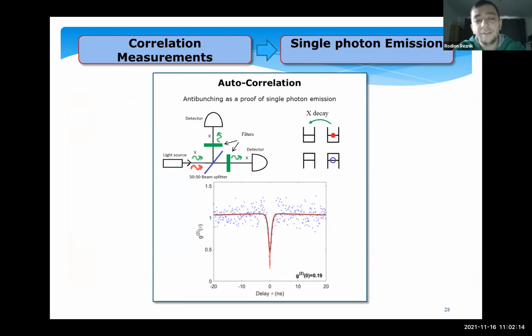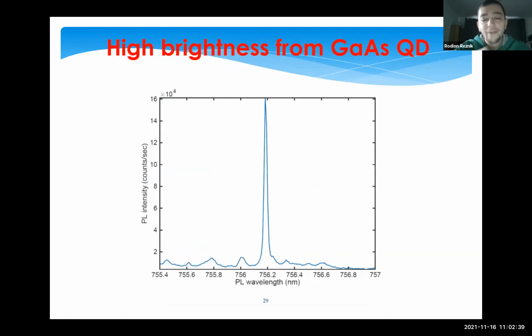Finally, we have done correlation measurements and have these results: zero time of the g2 function is 0.19. It is enough, I think, to say that we have single photon sources. This was done in DTU as well. And finally, we have not only single photon sources, but high brightness single photon sources. We have really bright single photon sources, because this number in counts per second is really high.